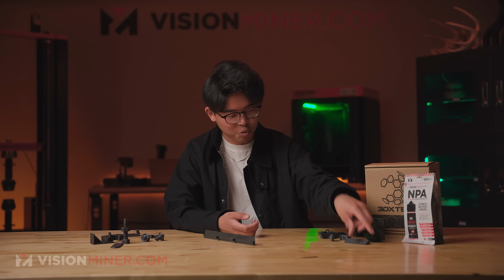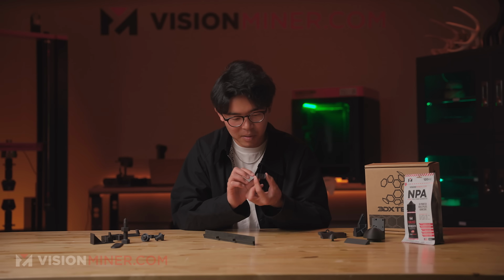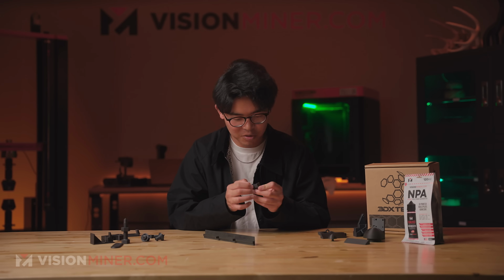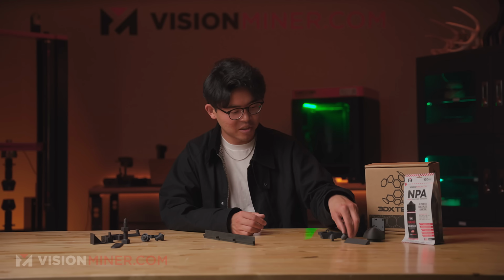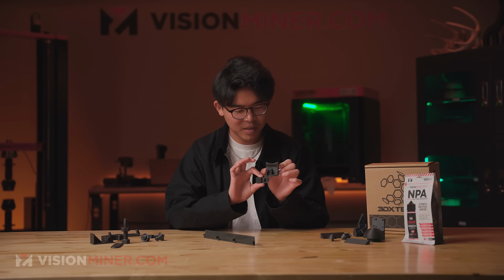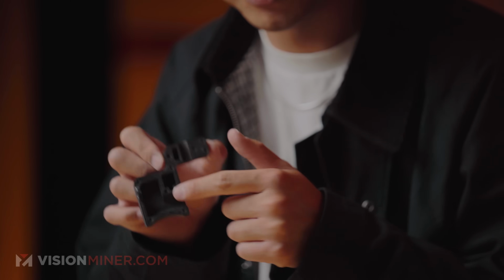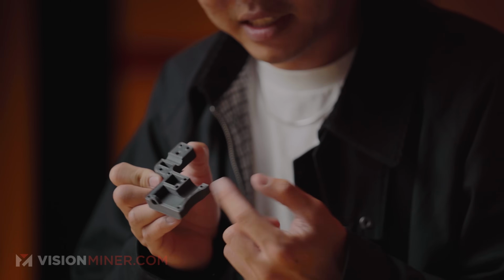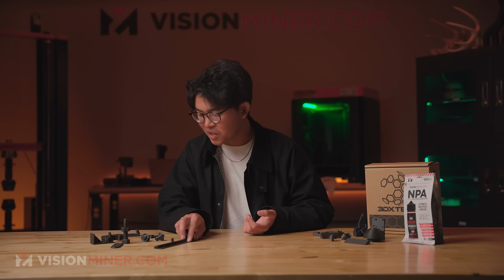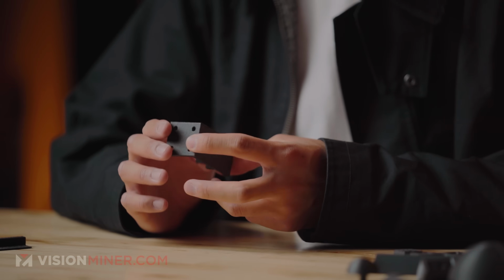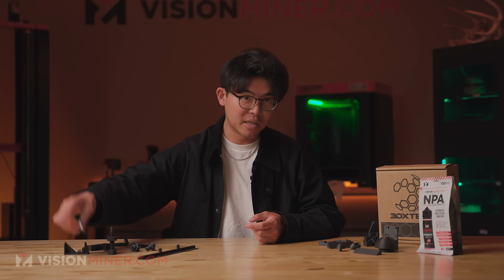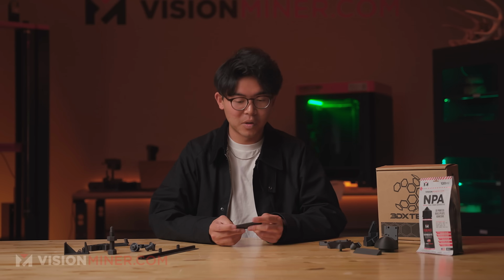This stuff is extremely easy to print. As you can see with some of the parts I'm holding here, it has a beautiful surface finish. It's incredibly dimensionally accurate. That's why you're seeing it used on a lot of these demo parts here, where precision and cleanliness is key. It needs very little post-processing compared to a lot of other materials, especially compared to PEEK. With PEEK, you definitely need to be a little careful with dimensional accuracy. It has a tendency to ooze and it's difficult to extrude, and so on. The carbon fiber fill actually makes this extremely easy to print compared to PEEK.